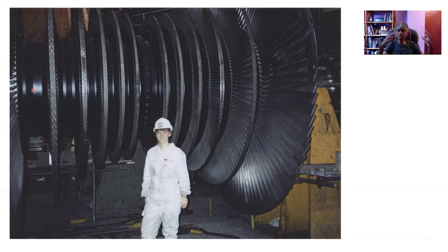So the typical steel used might be 2.25 chromium, 1% molybdenum weight by weight, and a certain amount of carbon. And then they are tempered in order to generate alloy carbides like molybdenum carbide and chromium carbides, which give it creep resistance and stability at the temperatures where this operates. So the steam temperature could be 600 degrees centigrade and the machine has to operate for something like 40 years. So with very large components, it's not possible or not economical to obtain martensitic structures. So continuous cooling transformation is the much preferred route of transformation, and therefore they tend to be bainitic. The other advantage of not quenching is that you avoid the distortions associated with a rapid change in temperature in a large component. So bainite is extremely important from a technological point of view, especially with heavy engineering.